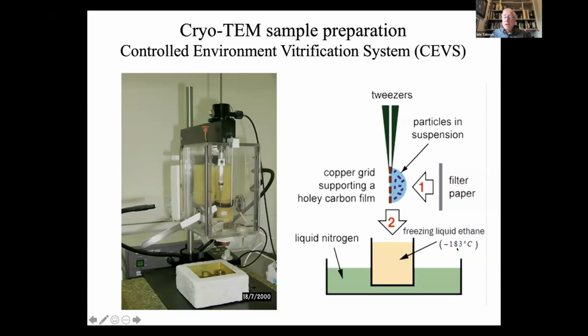The temperature is minus 183 degrees centigrade. The reason we use ethane is that the boiling point of ethane is about 100 degrees higher. So when we plunge our specimen into freezing ethane, we don't get any vapor film around the specimen, which assures us that we get a very high cooling rate, which should be for water about 100,000 degrees per second.